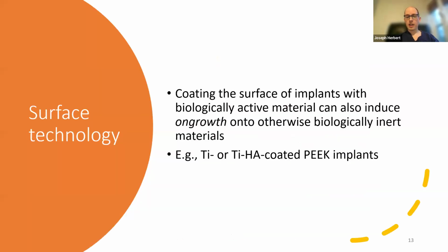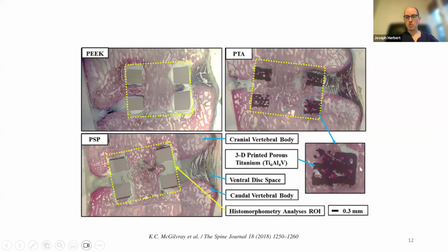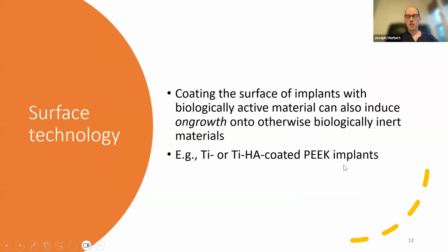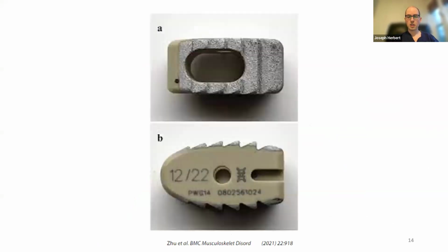Beyond making an implant out of a particular microscale or nanoscale structure, you can also coat the surface of implants with biologically active material, which can induce ongrowth. So this was ingrowth, of course, growing through the graft. But you can also coat these materials to induce ongrowth onto otherwise biologically inert materials. A really widely used example of this is titanium hydroxyapatite coated PEEK implants. So that's what these look like.